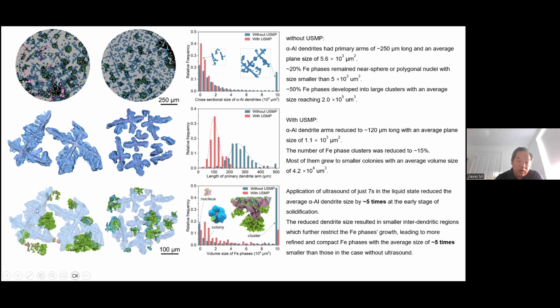This is without ultrasound, and you can see the effect on the dendrites with the ultrasound. Typically this dendritic structure was at least 50% smaller. Also, the iron intermetallic phase was again at least about 50% smaller. So it's very, very effective. You see the different distribution characteristics of those dendritic structures and those intermetallic phases. So we believe this ultrasound capability is a very important technique. It can be explored to help accelerate the recycling of aluminum.